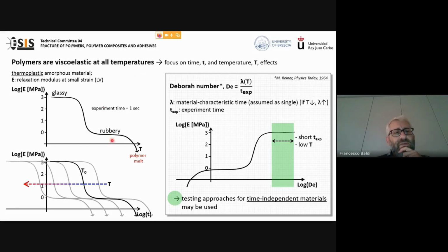In this slide, I have referred to a thermoplastic amorphous material and to its relaxation modulus. And in this graph here, I plot the variation of the modulus, that is an index of material stiffness, with the temperature. We can easily observe that from a modulus of plus or minus 1 gigapascal, the material goes to a modulus that is around 1 megapascal, that is typical of rubber at room temperature. This transition, where we observe this clear decrease in modulus, is the glass transition temperature.